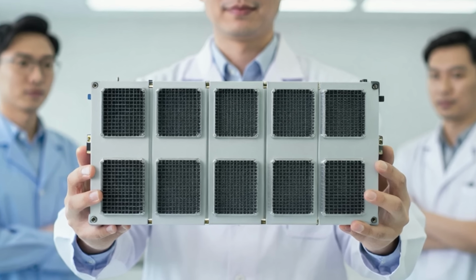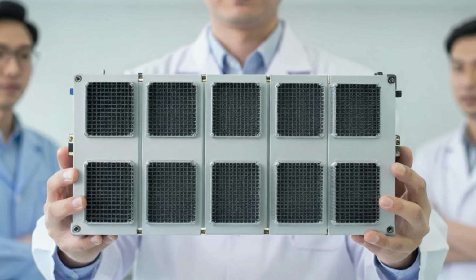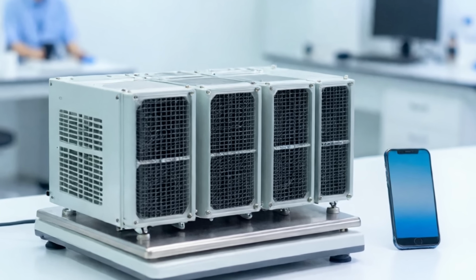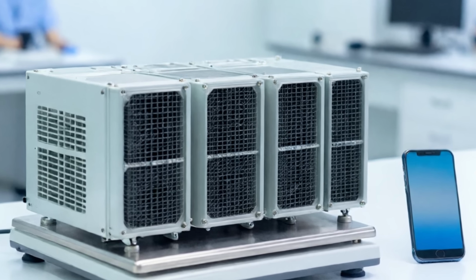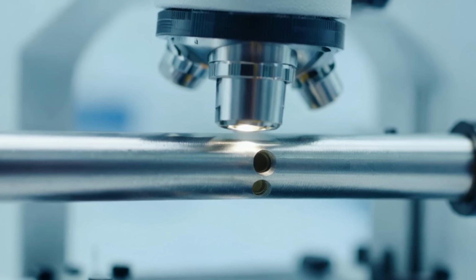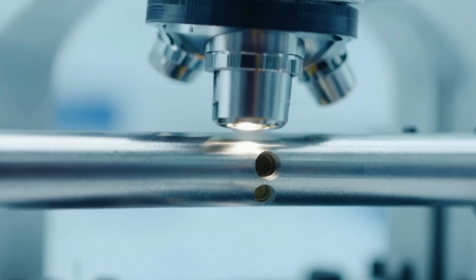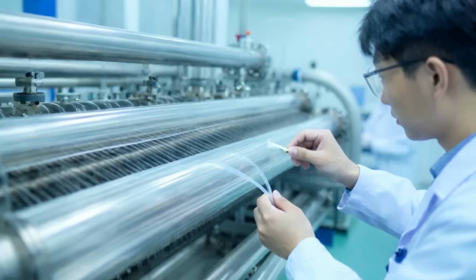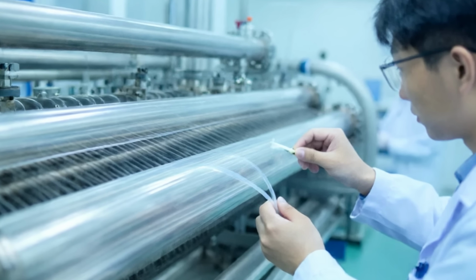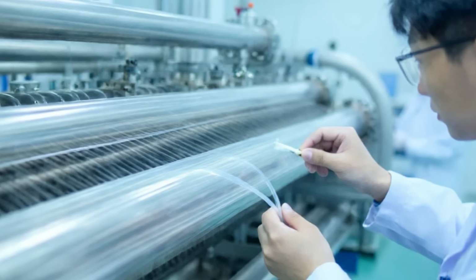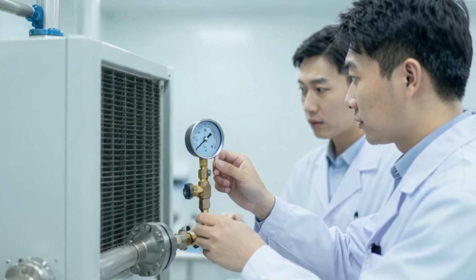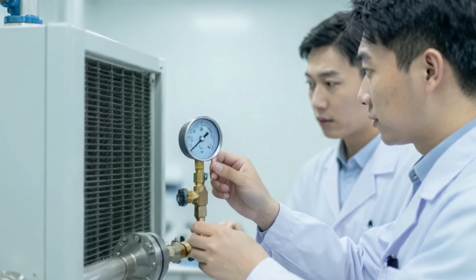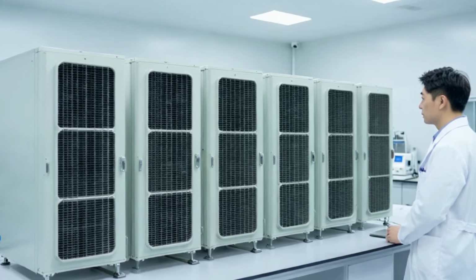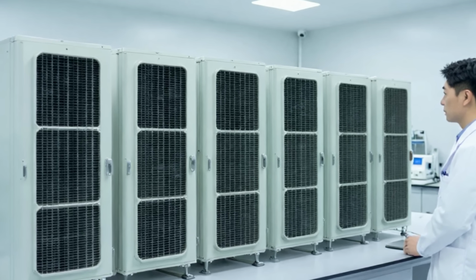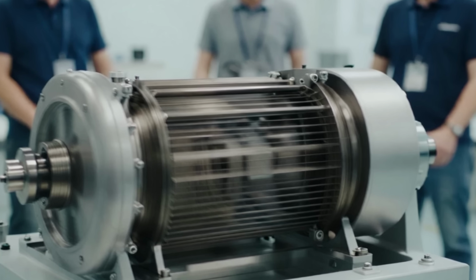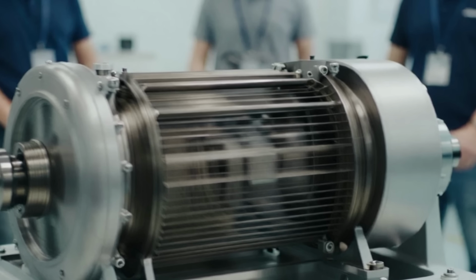The thin-walled tubes have a high surface area-to-volume ratio, which means heat can move in and out of the metal quickly. And instead of circulating all the fluid through a single path, the team ran parallel fluid channels alongside the units, keeping the internal pressure below 1.5 bar. That low pressure means the system can operate at high frequency, cycling 3.5 times per second, without the fluid channels becoming a bottleneck. But they didn't stop there. The team replaced the distilled water that previous designs used as a heat transfer fluid with something more effective, graphene nanofluid.